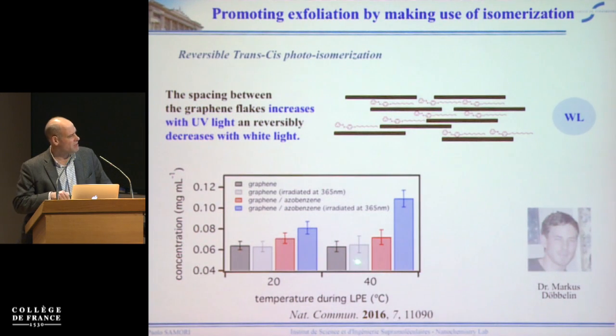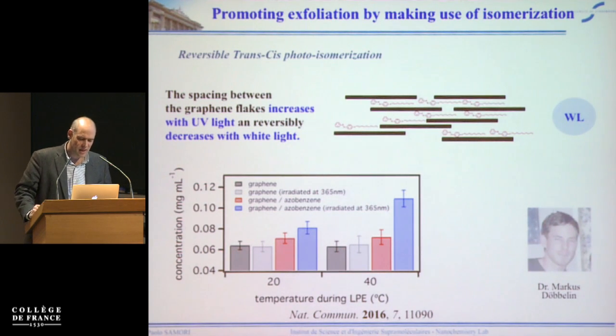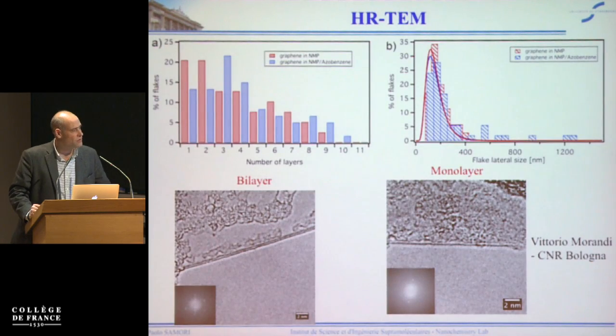You can play with temperature, but I will not go into that detail. You can just focus here. You can see that you have the yield of exfoliation that is changed while you irradiate your solution with UV light. So this is a bicomponent solution of graphene plus azobenzene that is intercalated between adjacent layers of graphene. Now, of course, again, you have to do all the characterization. Raman, in this case, was done by Andrea Ferrari in Cambridge. Electron microscopy was done by Vittorio Morandi. Again, you have mono, bi, tri, and a bit of tetra layer.